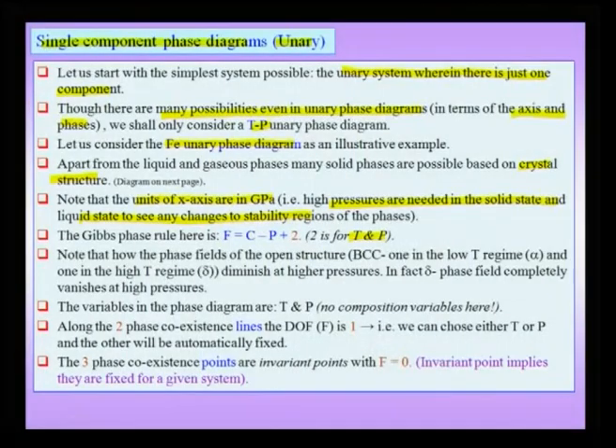Since temperature and pressure are two variables, the Gibbs phase rule is the extended phase rule, wherein F equals C minus P plus 2. That means the variable is not 1 as in the reduced phase rule, but the complete one with C minus P plus 2, and the component is just 1 because we are only considering iron.